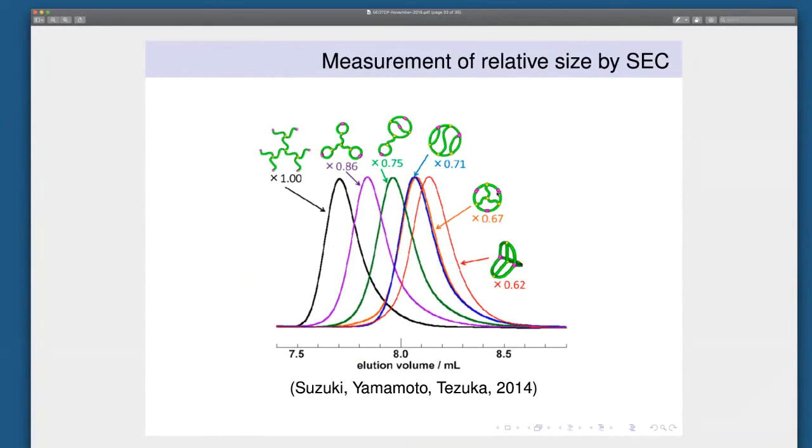you have to understand that this is like 17 consecutive fractionations later, so it takes something like 60 hours continuously to pull these things apart. And they just say, look, the order in which it comes out correlates really well with radius of gyration and hydrodynamic radius. So this is one way to measure it. The other way to measure it is neutron scattering, and we have other collaborators who are getting data that way. So we should be able to compare not just with size exclusion chromatography, but also with neutron scattering. Thank you.